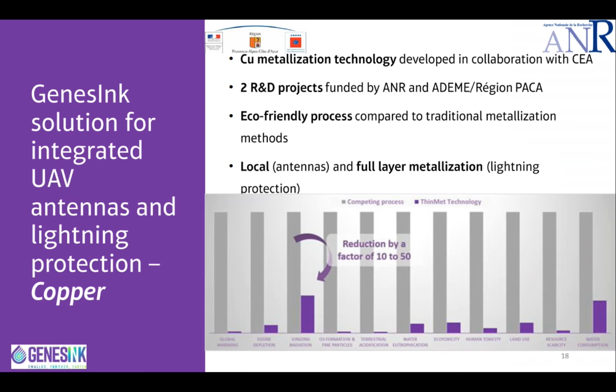An eco-friendly process was developed, reducing by a factor of 10 to 50 the key environmental indicators like global warming, ozone depletion, terrestrial acidification, water eutrophication, and so on, compared to the traditional metallization methods, most of them subtractive. With this additive process of substrate metallization based on an electroless bath technology, we can manufacture local and full layer copper metallization beneficial to antennas and lightning protection. Thanks to this more eco-friendly technology, we can reach very high performance on many different types of substrates, such as composites, PET, PVC, ABS, and Kevlar materials.